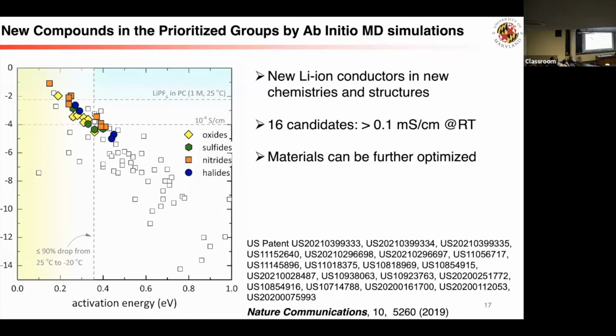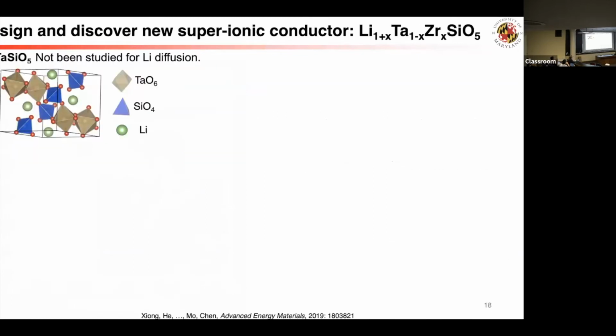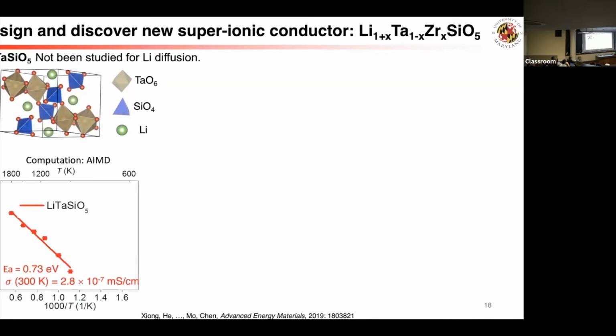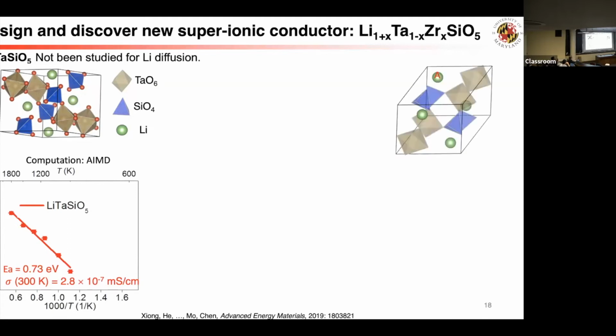There's also experimental confirmation. This is a material, lithium tantalum silicate, and its crystal structure looks like this. This material is known, but it has never been studied for lithium diffusion. If you just feed this original material to molecular dynamics, you find activation energy high and conductivity low. But if you analyze the structure more, you actually find there are more lithium sites that can create more lithium diffusion channels.